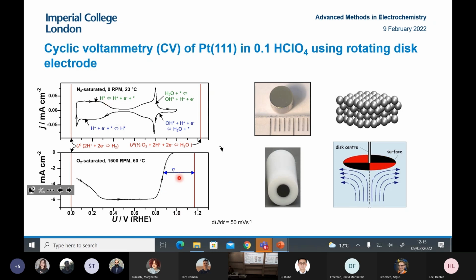And so the potential losses for the reaction are shown here. So the difference between the red and the black line, and they're quite substantial, depending on the current density, let's say around between 0.2 and 0.3 volts to get reasonable current density. And this is a problem for a fuel cell, of course, because it means you can't operate a fuel cell